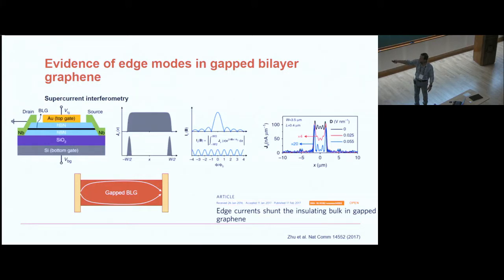So what happens is they came to a conclusion that in the gapped bilayer graphene, the gap is far more insulating than the edge. Okay? The current actually flows along the edge rather than through the bulk. And that was very interesting. And they claim that the edge current shunts the insulating bulk in the gapped bilayer graphene. Very similar to what happens in topological insulators, but there, of course, it's nearly e squared by h, nearly perfect conduction.